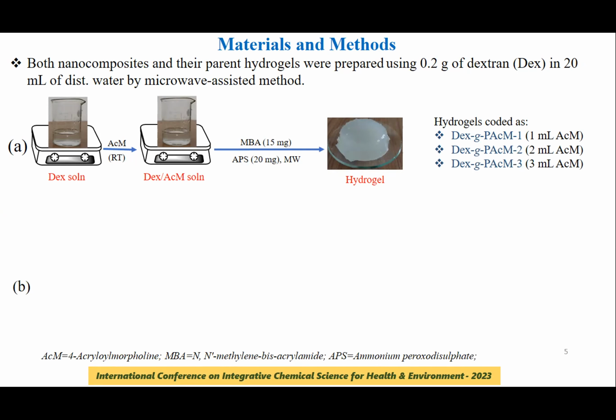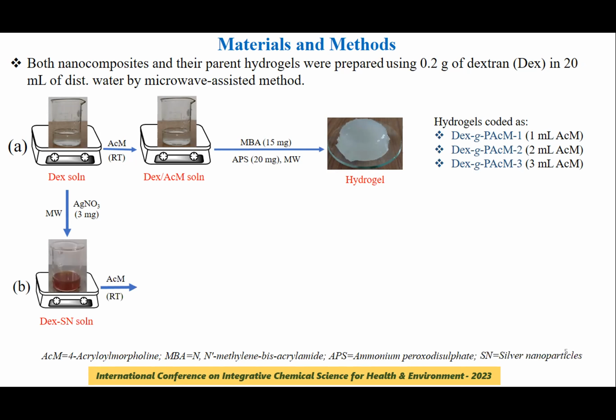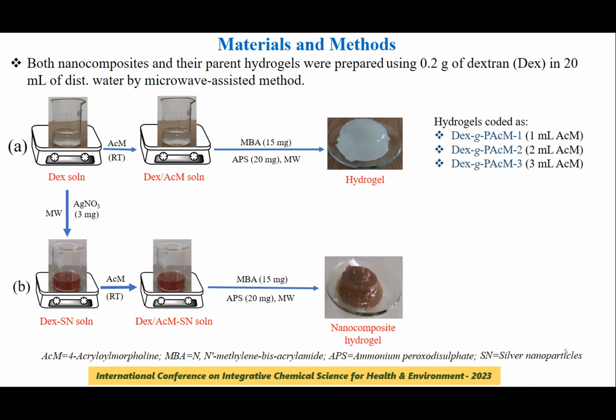In the synthesis of the nanocomposite, a similar approach was used, except that silver nitrate was added before the addition of monomer, crosslinker, and initiator. Upon addition of silver nitrate to the dextran solution, the solution was irradiated in the microwave and it turned deep brown, indicating the formation of silver nanoparticles. Thereafter, ACM, MBA, and APS were added, followed by microwave irradiation to get the nanocomposite hydrogel. Similarly, this nanocomposite hydrogel was coded based on the amount of ACM used: 1 ml, 2 ml, and 3 ml.